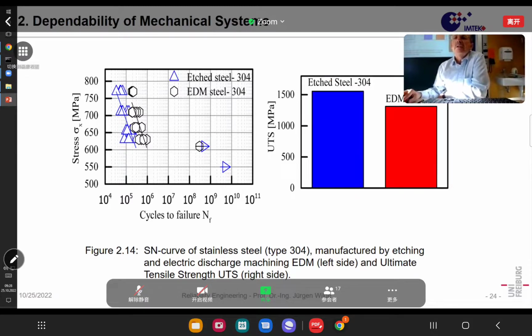What you can see, the etched part was stronger than the EDM, but the EDM was somewhat better, so it tolerated significantly more cycles than the etched steel. That's a little strange, because normally you would expect, from what I told you previously, that the stronger steel here that has 1,500 megapascal as a strength should also be better at fatigue. But here you can also say the surface has an influence, and probably that EDM created some, you could say, compressive stresses in the surface. On the other hand, the endurance limit is roughly 600, you could say.